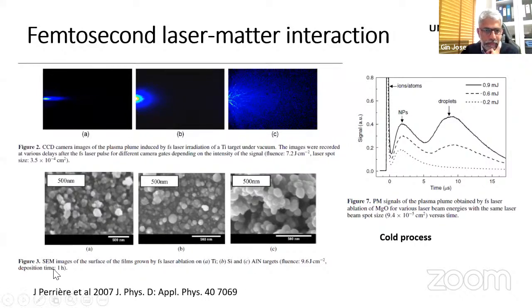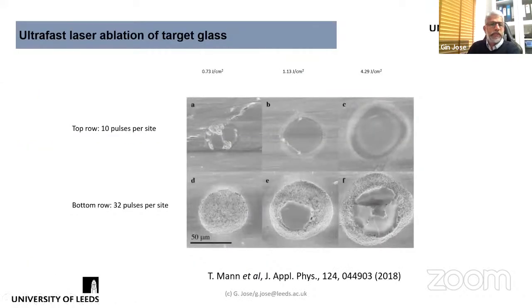This is from this reference. It shows the effect of ablation on different targets, like titanium, silicon, and aluminum nitride, at a given fluence. It's material dependent, and you need to control the fluence for each material to get a uniform distribution. But in each case, you see more material deposited as particles, and the particles will also form clusters. So you need to control the fluence, the laser energy per unit area at the target, in order to get uniform ablation. That's the first step in optimizing the laser deposition process.